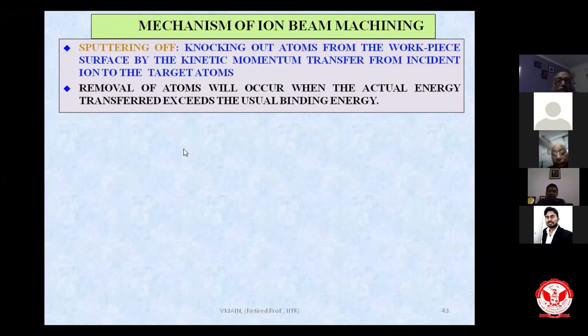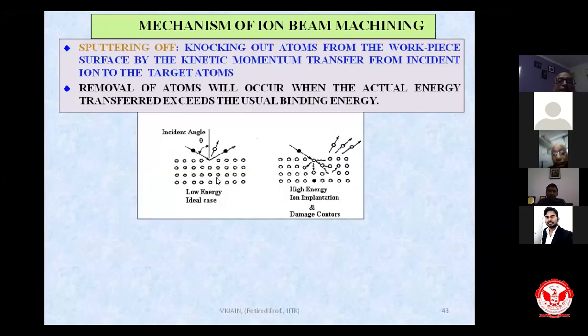Now you can see here, this is the incident angle theta, and this is the ion which is coming over here. The kinetic energy of this ion is just equal to the bonding energy of the atom. One ion is able to remove one atom, and therefore this is the ideal situation, low energy ion beam machining. This is the ideal case which we want. But in real practice, it does not happen. The kinetic energy of these ions is very high. One ion removes many atoms, as you can see over here, and it gets implanted. Once it gets implanted, this becomes damage to the structure. We don't want this kind of feature to take place.